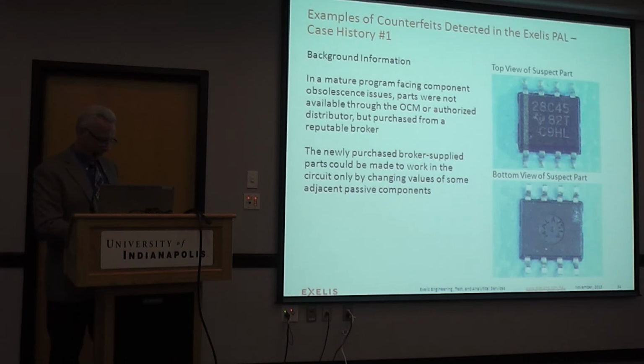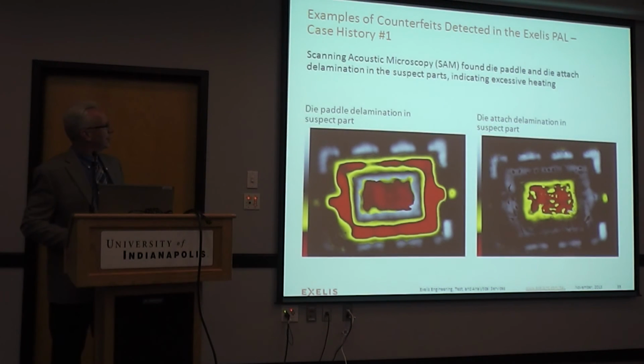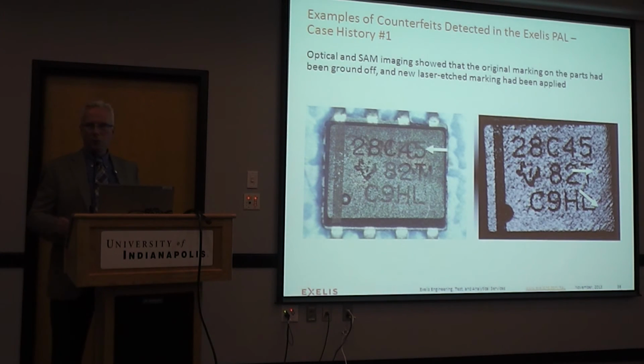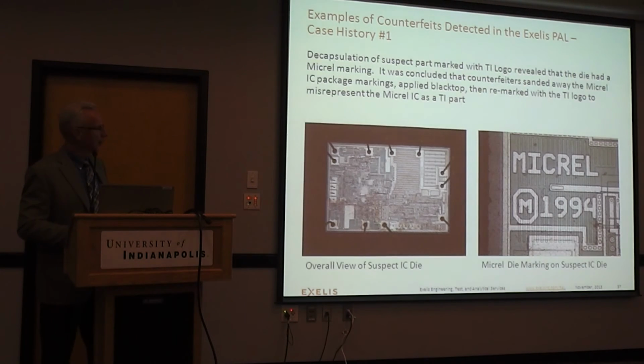And we looked into it further, and we found die paddle delamination. This is where we're using the scanning acoustic microscope to look inside. This delamination can happen very easily when you take parts off of a reclaimed board. But when we looked further and did a optical microscopy technique, we were able to see grinding marks underneath the blacktop coating. And you can see a little bit of ghosting of prior markings. So this is where a good optical microscope can really come in handy.